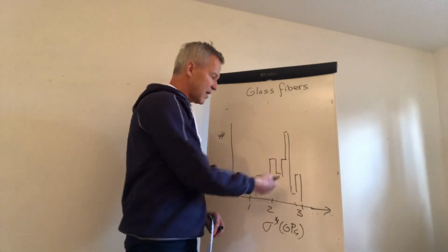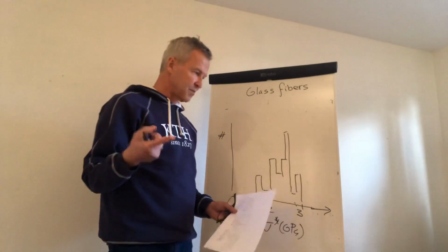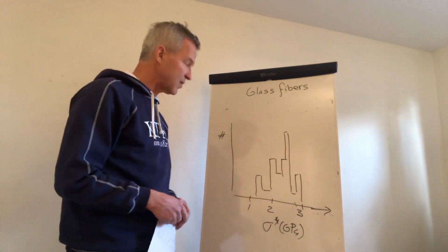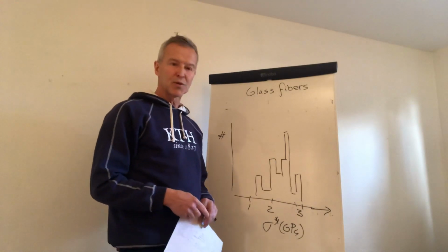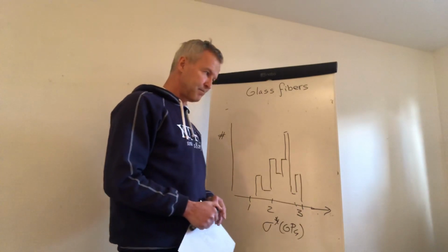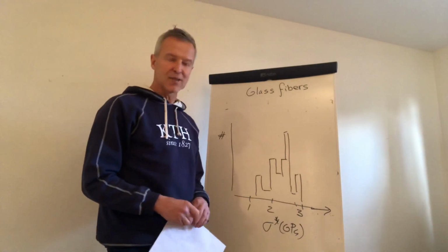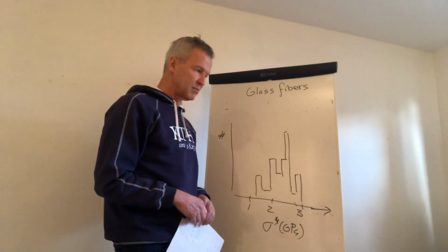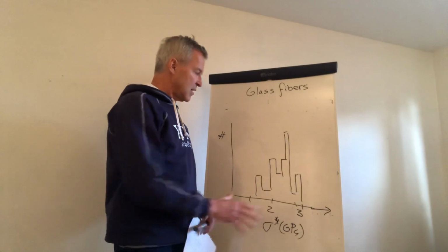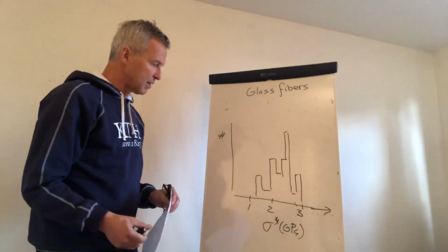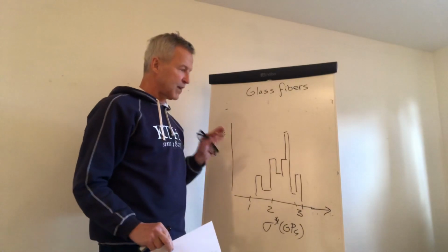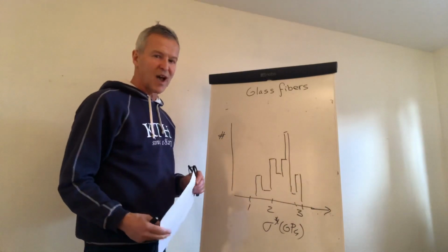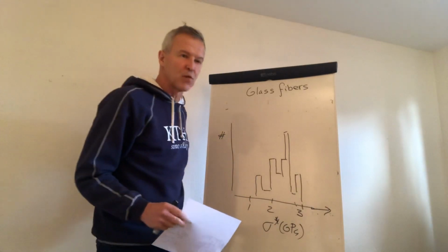And in the case of glass fiber, the reason is that you have surface defects on individual fibers because of handling most of the time. They're also susceptible to chemical attack. So if you have moisture present and you don't protect the surface, there will be defects forming on the surface. So this, I think, is very important. Another manifestation of this phenomenon is that if I change the length of my fibers, I will measure different values for strength.